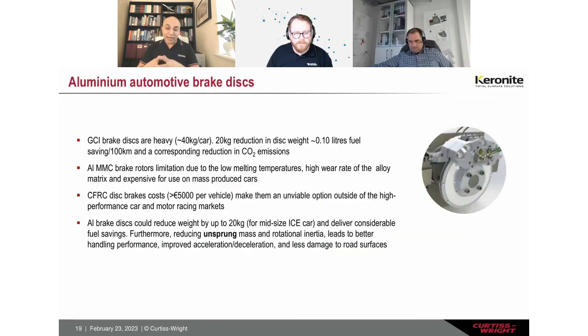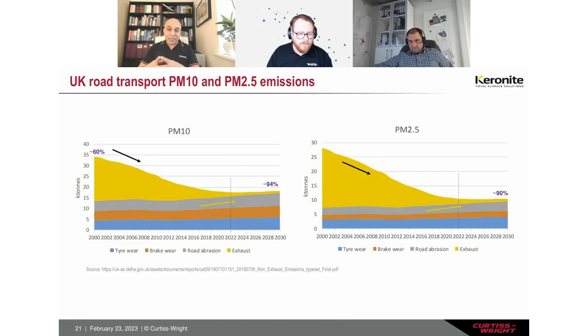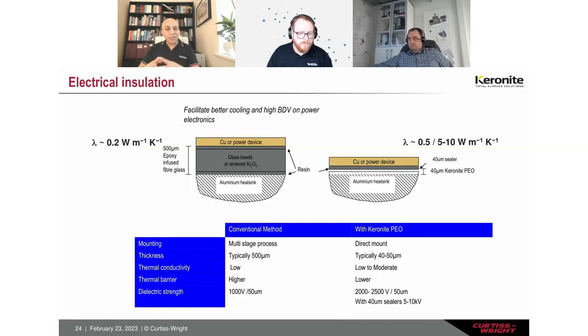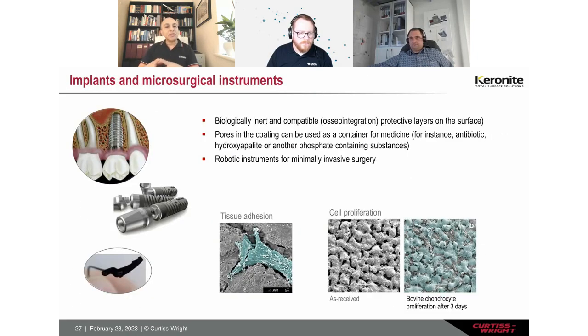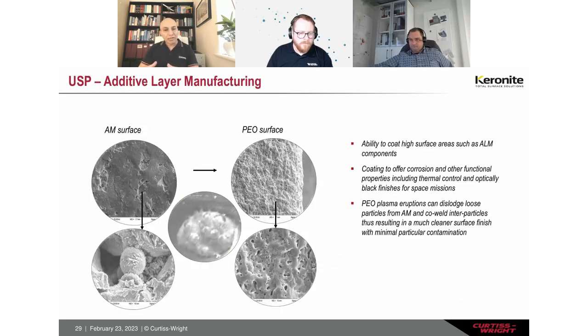Very good question again. As I said before, yes, PEO coating will generate some roughness and it will reduce the fatigue strength, but not to the extent of a hard anodized coating. But if you are already reducing the fatigue strength by, for example, 80-90% with those large cracks and porosities in the additive manufacturing component, and you fill those holes with PEO, coalescing and minimizing those cracks, it's bound to give an improvement, not a reduction. Of course, you cannot benefit 100%.